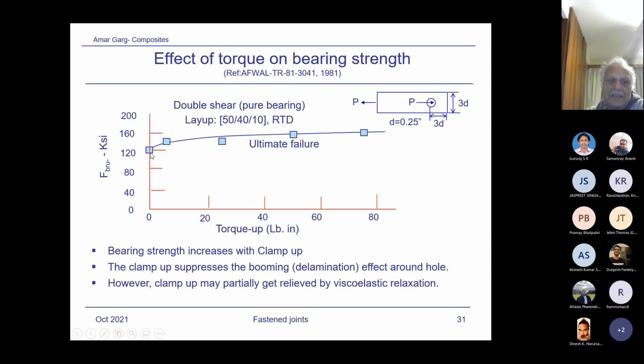And as you can see, based on the torque value, when the torque is 0, like finger tight only, there is no clamp up. You have 120 KSI as bearing. Now, bearing is defined as the load divided by thickness divided by the diameter. P by dt is called the bearing stress. And as you can see here, as we increase the torque, and this is fully torqued here, the value is 160 KSI almost. So you can see from 120 to 160 KSI, that means an increase of 40 KSI, which is over 30%.